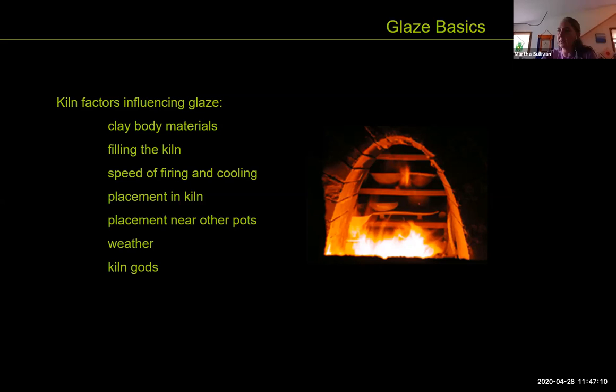Placement in the kiln or placement near other pots. When we talk about wood firing in just a minute, how close you are to the heating element, or if you're near a pot where there's a glaze that fumes, like copper fumes. Do you remember that Stacy said that black glaze fumed onto her kiln shelf and turned it blue, and then she started using kiln wash on her pot? So there's cobalt that's literally being released as little tiny molecules inside of the kiln. And then if there's another glaze that's hot and excited, then it'll grab it and it can change its color.